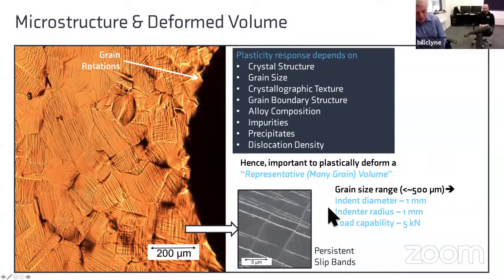And what that translates into, if you recognize that the grain size could be anything up to 0.5 millimeter or even more, but this would be a typical range up to, say, 500 microns. That means you need an indent diameter, which is at least around 1 millimeter, and probably an indenter radius of around 1 millimeter as well.